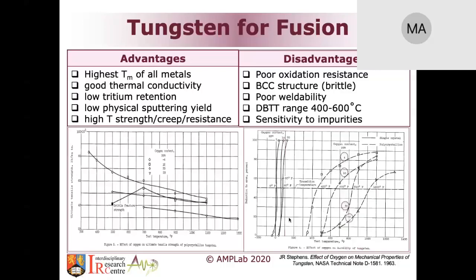Again, that's a similar figure to the previous one. It shows the oxygen content and how it changed from 4 parts per million to 10 parts per million to 30 to 50. And again, we're looking at the reduction in area during mechanical testing. As you can see, oxygen additions are in general bad news, not good for the mechanical properties of tungsten.